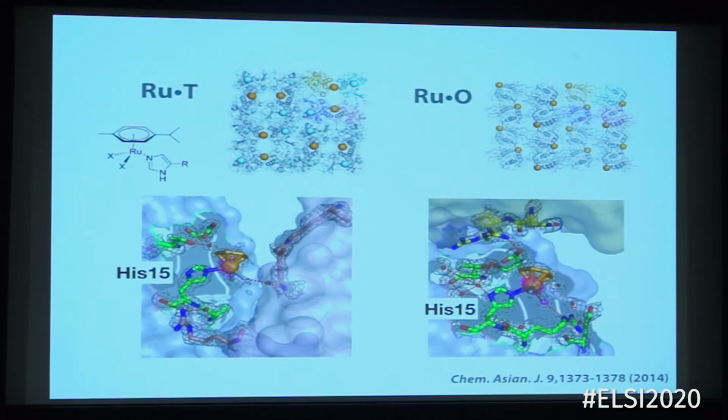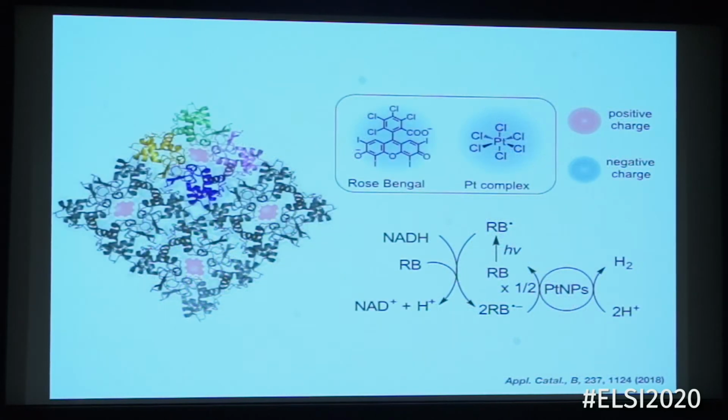That's why, when the substrate accesses the bound catalytic center, the direction should be different in the two crystals. So this is one of the reasons why the orthorhombic crystal and the tetragonal crystal proceed with this catalytic reaction with opposite enantiomer selectivity, right? This is one demonstration of constructing a heterogeneous artificial metal enzyme. This is applicable to different types of construction of heterogeneous artificial metal enzymes.